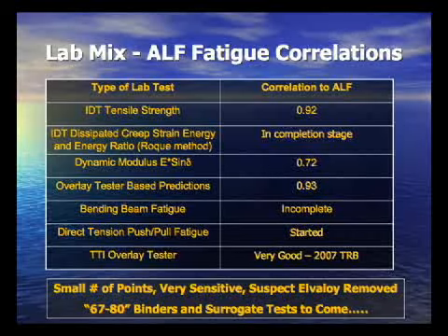For fatigue characterization, IDT tensile strength provided a fairly good correlation, but we need to expand to more mixes. The dissipated creep strain energy, this is Ray Roque's method from Florida. That is in the completion stage, and that could also be a good simple performance test for cracking. It's very simple to do indirect tension. Dynamic modulus provided somewhat of actually a pretty good correlation, but again, it depended on what thickness you were looking at. I'll also pause here for a second and say a lot of the details are in the paper, and I suggest you can go there. But I wanted to highlight what's going on.